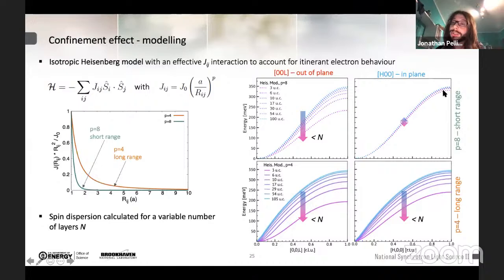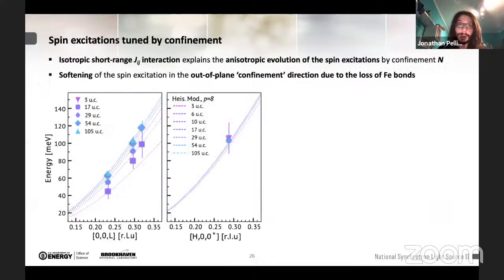So these latter parameters were able to explain our anisotropic response. And based on these calculations, we compared our experimental results with this Heisenberg model. And I'm showing here the results.